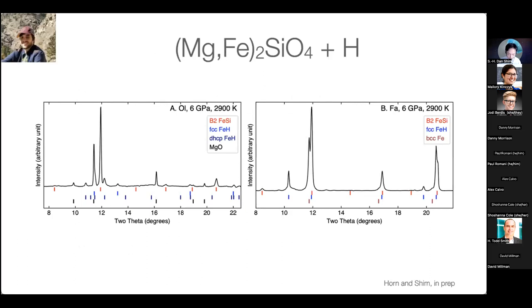The next question we would like to address through our experiment is to study minerals that have silicon in them. Magnesium, silicon, and iron are the major cations of the rocky part of the planets, so one can view this as a more realistic case. So we used olivine as a magnesium silicate proxy mixed with hydrogen, the same way we did for the MgFeO mixed with hydrogen experiment. Now you're looking at, again, X-ray diffraction patterns. The peak positions indicate what phases are formed. The bottom peaks show the theoretically calculated peak positions of different phases.